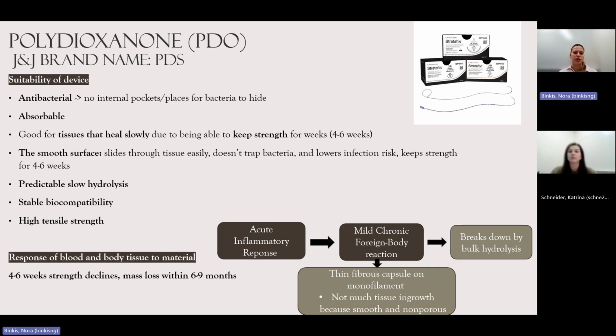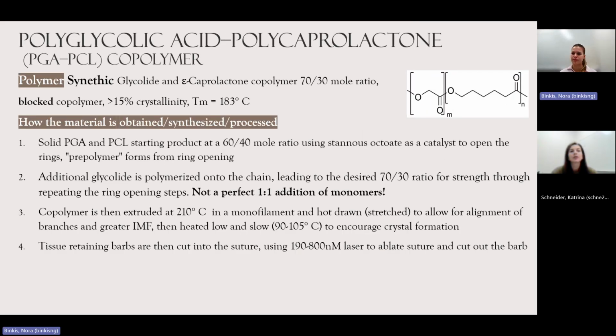And then for the response in the body, after about 4 to 6 weeks, the strength declines, and then there is complete mass loss within 6 to 9 months. So this starts off with an acute inflammatory response, and then goes to a mild chronic foreign body reaction. So there's a thin fibrous capsule that's created around the monofilament, but then this suture will break down by bulk hydrolysis. So mine was polyglycolic acid and polycaprolactone, or PGA-PCL copolymer.